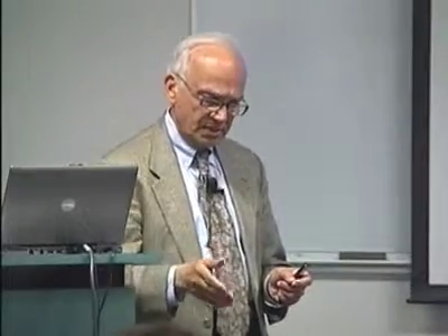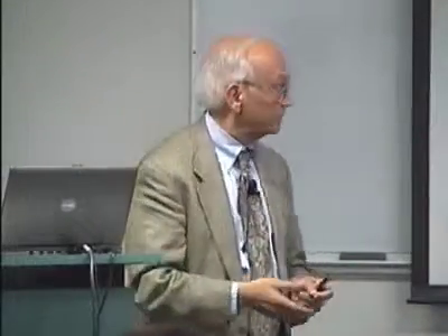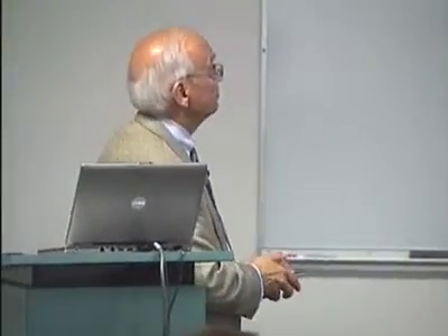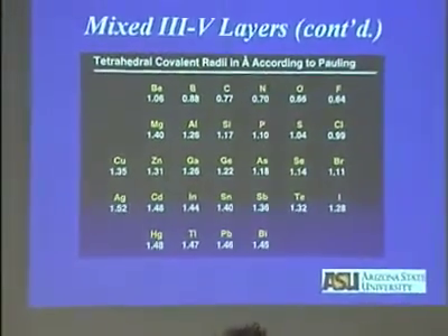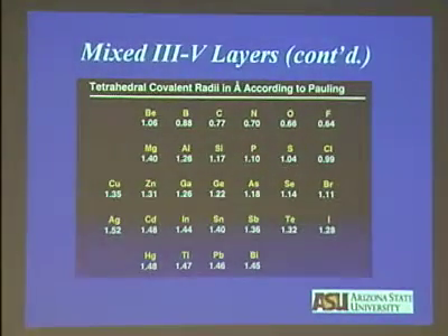And summing it up, phase separation occurs and is two-dimensional in nature in these indium gallium quaternary layers, occurring along the soft directions lying in the plane. There is no phase separation along the growth direction. And the wavelength that you see is of the order of, I will say, 8 nanometer, in the structure that is produced. Now, why does it occur? There are strain-related reasons. This is a table due to Pauling. You look at the tetrahedral covalent radius of gallium and the covalent radius of indium. The indium atom has a much larger covalent radius than the gallium atom.